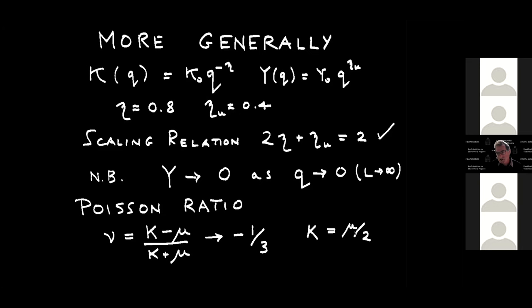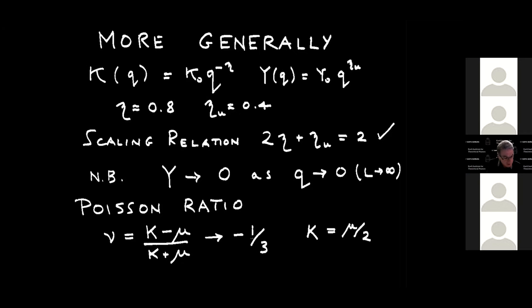It's a very unusual system because the elastic moduli go to zero at infinite length scales — very floppy — but with a well-defined limit. The Poisson ratio in this limit is quite unusual: the bulk modulus is smaller than the shear modulus, giving a Poisson ratio of minus one-third. When you pull on it you iron out all these entropic corrugations and fluctuations, and they spill out in the transverse direction, giving it a negative Poisson ratio. As the length scales get bigger, the bending rigidity grows, which flattens out the system.